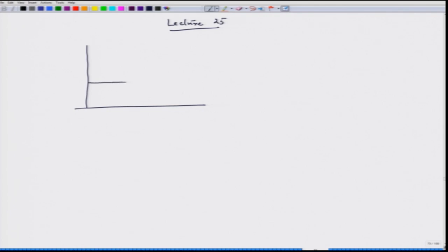In the last lecture, we ended with the schematic phase diagram for aluminium. We have given all the reactions as well as standard chemical potential for all the species active in those reactions, and from that you need to calculate that phase diagram, but the schematic will be like what we have shown in the previous lecture. The schematic phase diagram for aluminium would be this one, where this is Al3+, this is Al, Al2O3, and then this becomes AlO2-, and this is potential axis, pH axis.